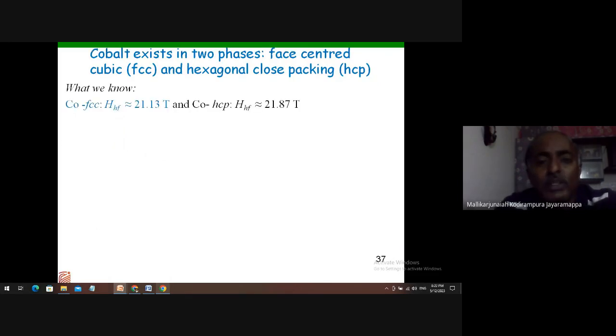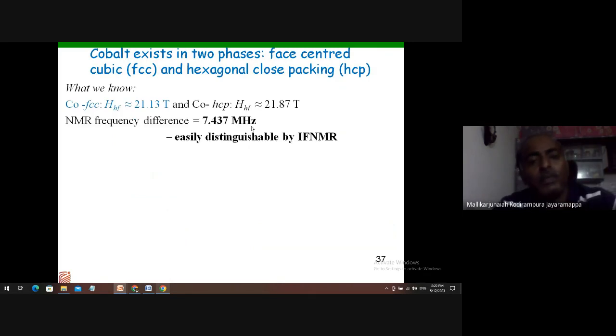And another thing I need to highlight here is, for example, you assume that you synthesize a compound and that compound has two phases. One is, for example, cobalt. When we synthesize cobalt, it forms both in the FCC and HCP phase. Now, whenever I perform the NMR measurement, I will get an independent peak at 21.13 Tesla when cobalt follows the FCC structure. Whenever cobalt follows the HCP structure, the internal field increases to 21.87 Tesla.